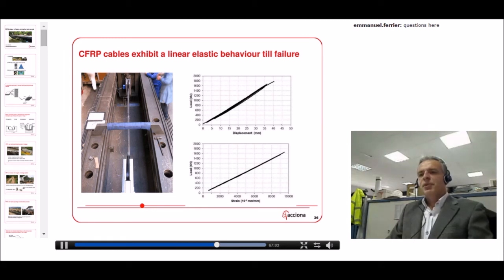We performed some tests on these cables, because these cables are normally used for sailing boats, but for sailing boats with a very small diameter. Such big cables hadn't been tested before. So before using them, we decided to perform tests. You see a tensile test, and you can see that the behavior of this cable is linear elastic till the failure. This is the curve in terms of load and displacement, and this curve represents the load and the strain measured at mid-span of this cable. So the behavior is perfectly linear elastic.